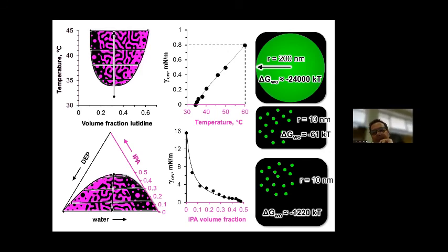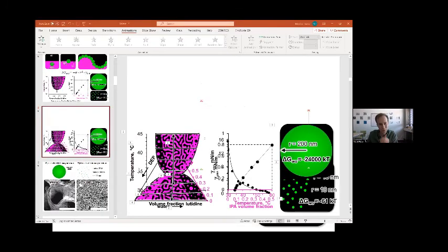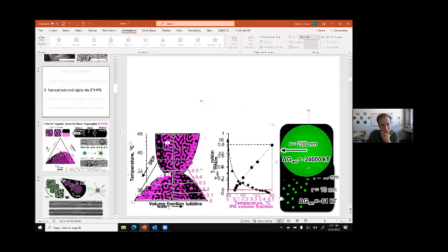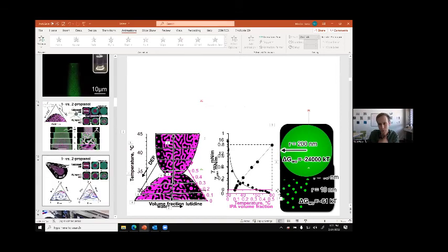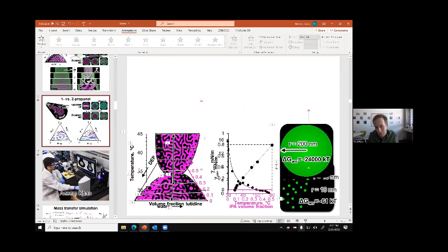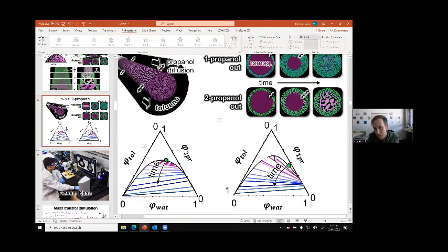I think with the system of 1-propanol versus 2-propanol, we have approximated this situation, because when you look at the phase diagrams of 1- versus 2-propanol here, you see the tie line is so steep, and that means that the oil phase and the water phase are very different in composition. That gives it a higher interfacial tension right away. Okay. Thank you.